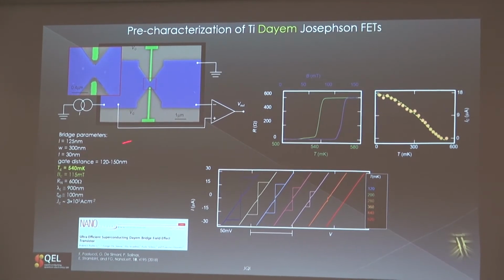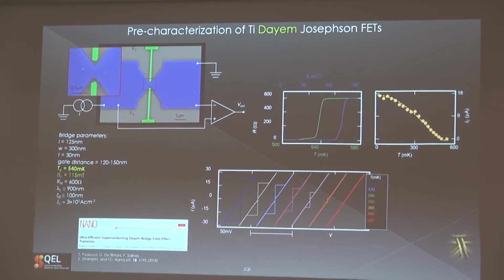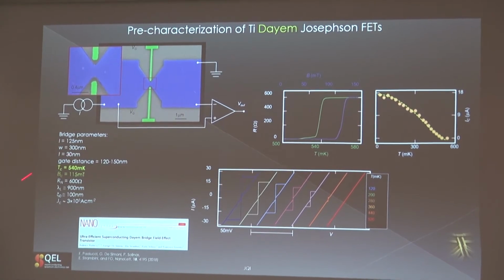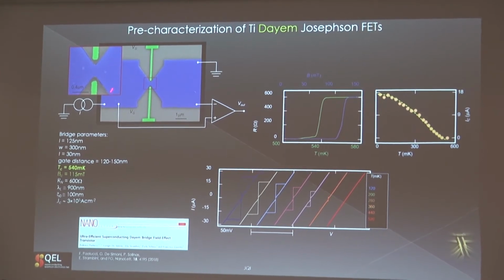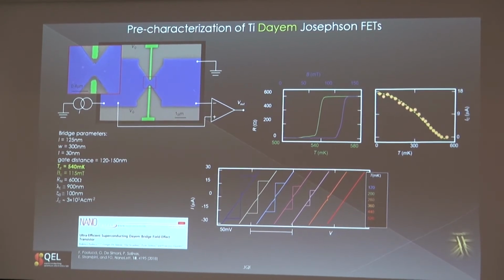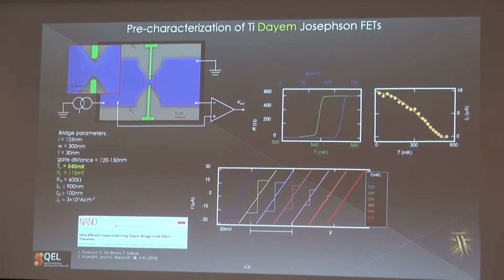Okay, here what we obtained was a pretty nice titanium, in the sense it was evaporated. We discovered how to improve the characteristics of these films, improving the critical temperature up to 540 millikelvin and the critical field of 150. Okay, and this thanks to a base vacuum condition of 10 to the minus 11 torr in the deposition chamber and extremely high deposition rates. But this is not very interesting in some sense.